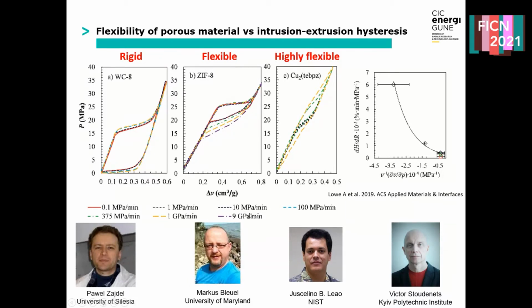On the other hand, for the more flexible materials like the ZIF-8 metal-organic framework and this copper-based metal-organic framework, which I mentioned before, the hysteresis changes drastically as the flexibility increases. So, for example, in this case, you can see that a non-hysteretic material actually converted into something which can be called a shock absorber, because the hysteresis is very, very large here. So it's very curious for us to see how it affects the electrification during the intrusion-extrusion process.